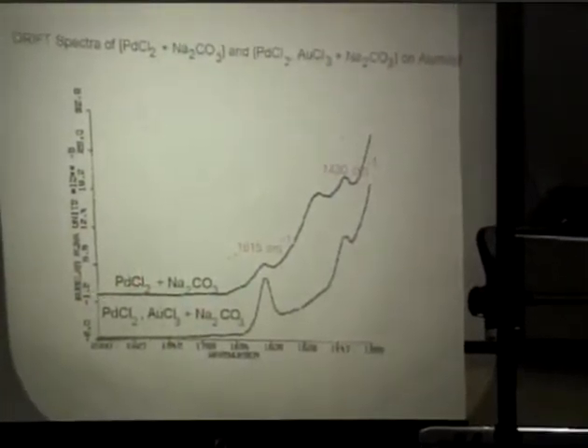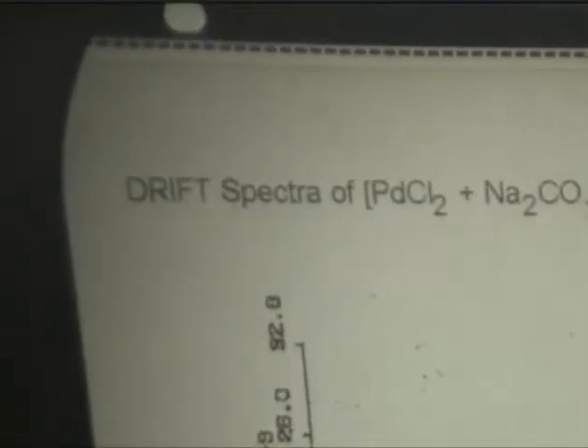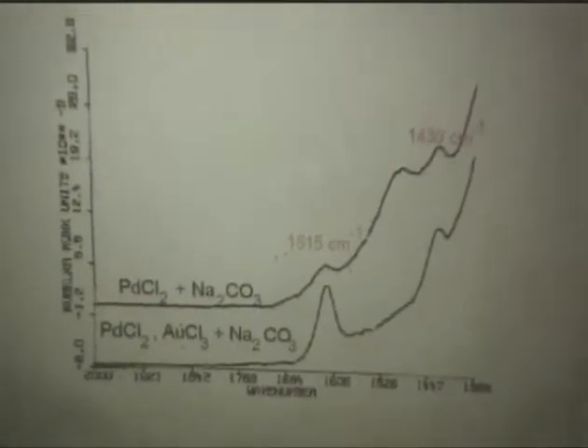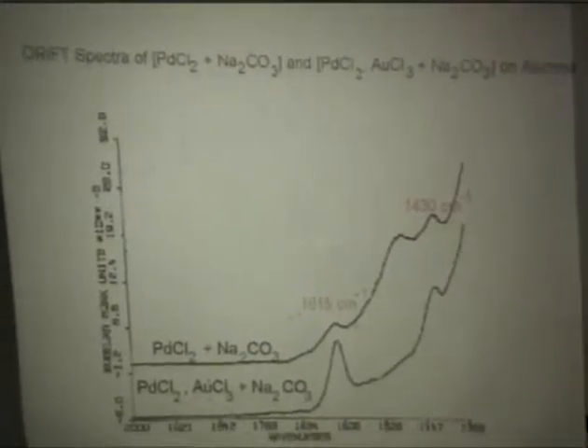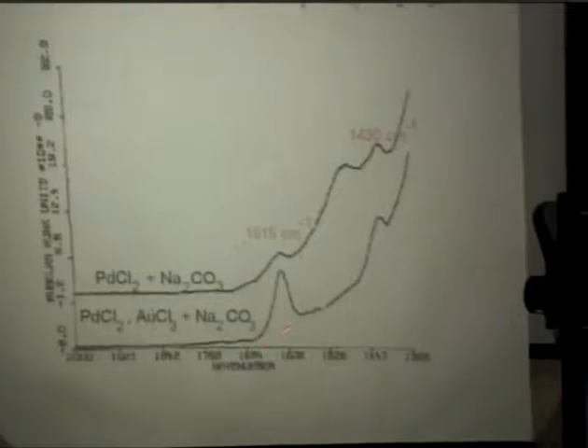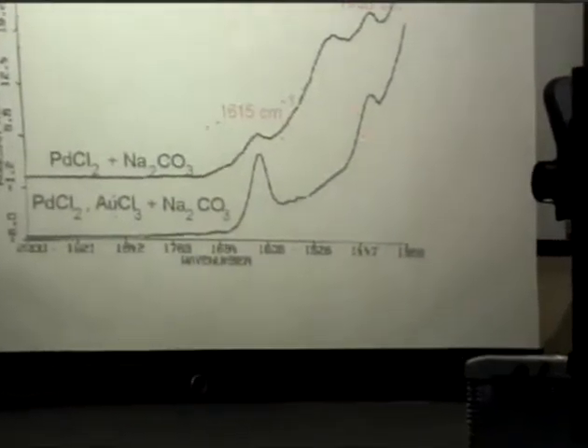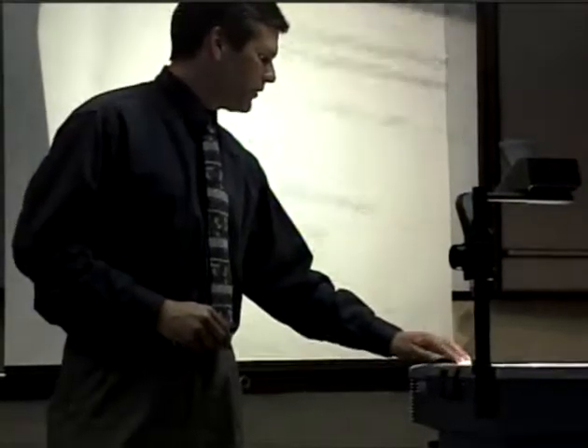Do the same thing with palladium. And again, as we titrate that carbonate, we see that we get a doublet, two bands of the palladium, what we think is some type of palladium carbonate type species. We don't know what the structure is at this point, but also the sodium carbonate. And then as we titrate the entire sodium carbonate presence, we see the bands here at 1615 and 1430 much more pronounced and apparent. So again, we see with just a simple titration that it appears we make a carbonate, and then with infrared, we see something that looks like a carbonate.